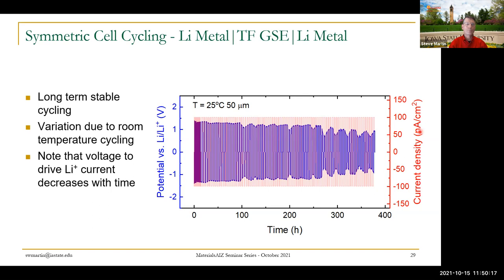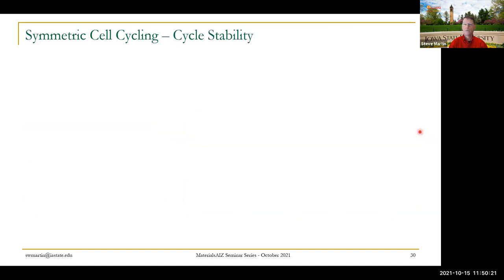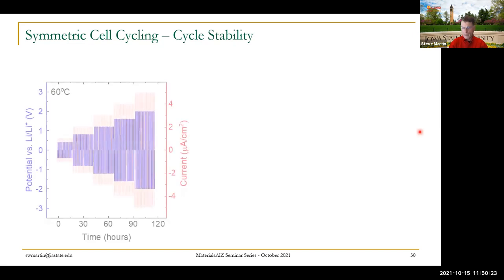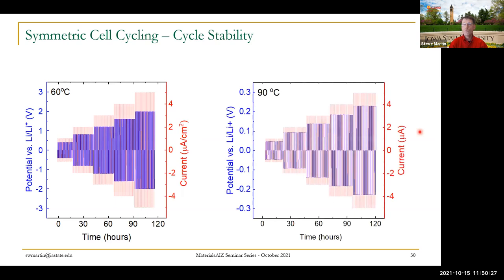gives us proof of technique and proof of a concept, but nonetheless capable. And then finally, if I'm okay on time, just two more slides, we can cycle. We warm these samples up a little bit because the conductivity of the oxide is pretty low. And you can see they're just perfectly square. Remember, this is 50 microns of glass.